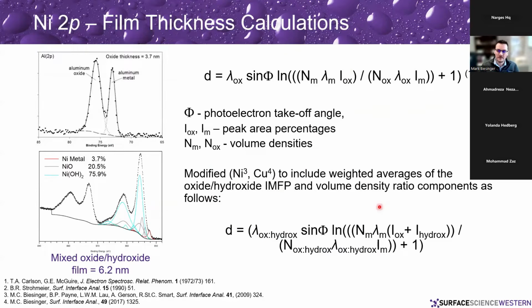So now that we've pulled out that sort of information, what are some of the things that we can do with that? You can do depth analysis calculations. If you have a system where you can see the metal underneath and an overlying thin film oxide or hydroxide on that surface, you can use calculations such as those developed by Strohmeier and Carlson that allow you to plug in the area under the curve.